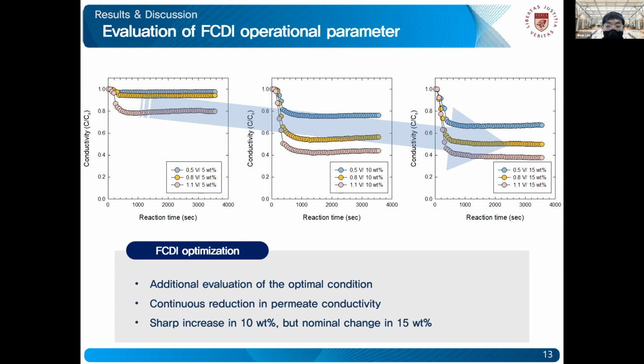As you can see from the left-hand figure, that is the increase in the voltage under a 5 weight percentage condition. And the middle figure is the increase in the voltage under 10 weight percentage. Now, the conductivity performance sharply increased from 5 weight percentage to 10 weight percentage. However, increasing the mass loading from 10 to 15 weight percentage showed a nominal change. And since a 15 weight percentage would only lead to the increase in the energy consumption of the system, we thereby confirm that the 10 weight percentage is the optimal concentration for the flow electrode parameter.